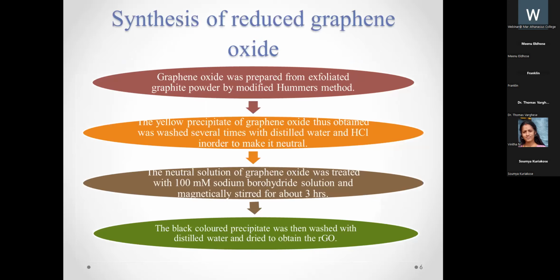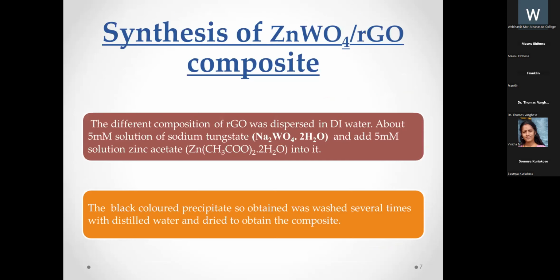Synthesis of reduced graphene oxide: graphene oxide was prepared from exfoliated graphite powder by the modified Hummers' method. The yellow precipitate of graphene oxide obtained was washed several times with distilled water and HCl in order to make it neutral. The neutral graphene oxide solution was then treated with 100 millimolar sodium borohydride solution and magnetically stirred for about 3 hours. The black colored precipitate was then washed with distilled water and dried to obtain the reduced graphene oxide.